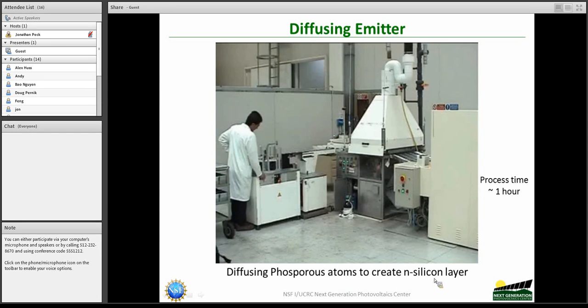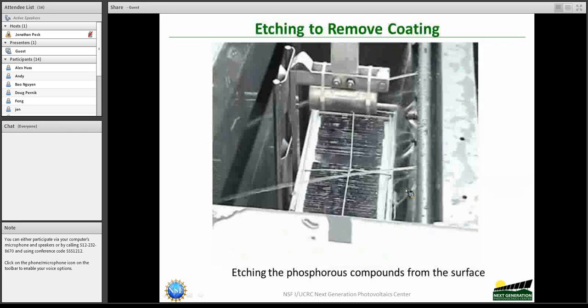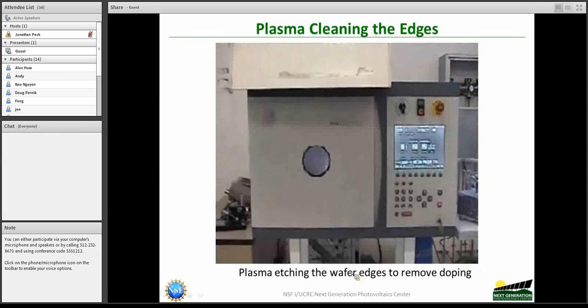As we saw in the structure before, the PV device involves a P-type wafer with a small N-type region on the surface. And that is what is being produced in this process step. And then the coating that created the phosphor compounds has to be removed, and there is an etching involved to remove the phosphor compounds. This particular process of doping the wafers also dopes the edges, and the edges can lead to some shorts if they are not cleaned.